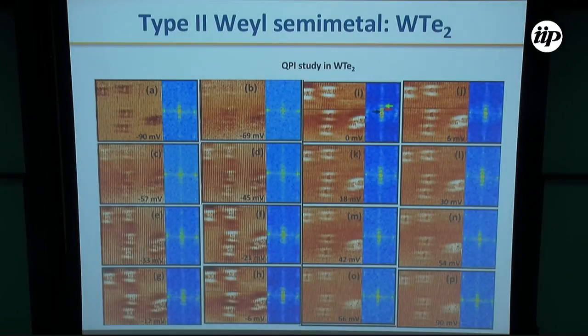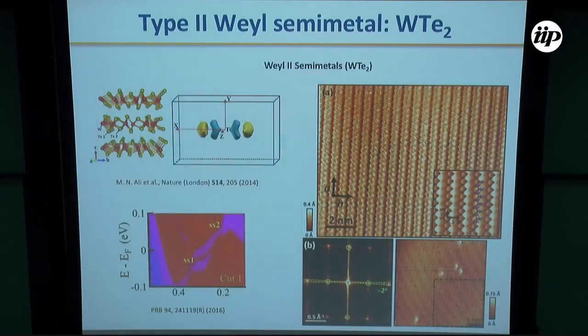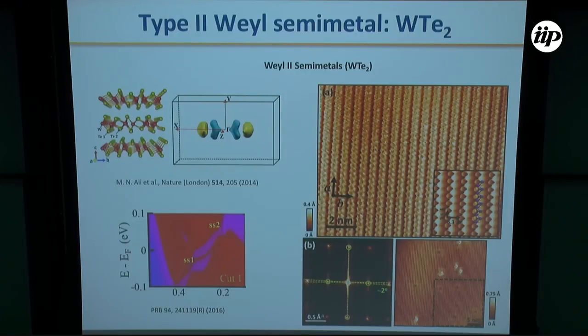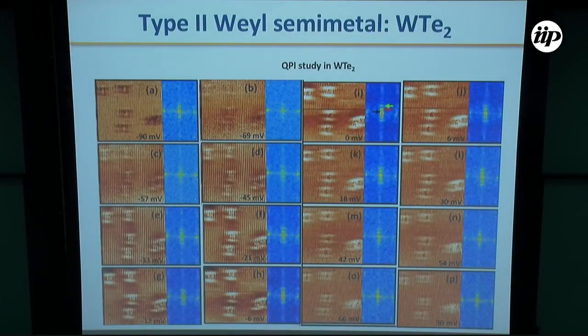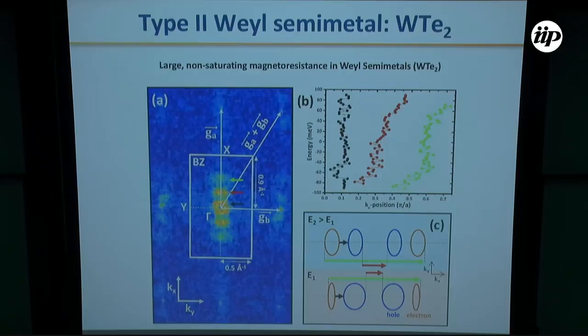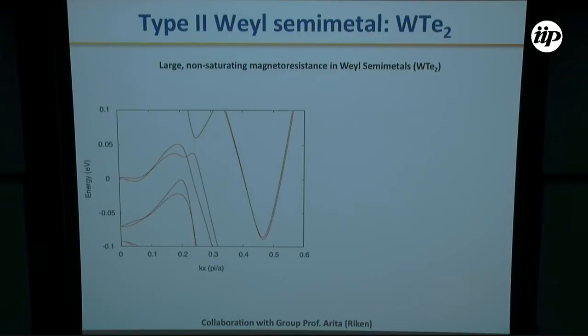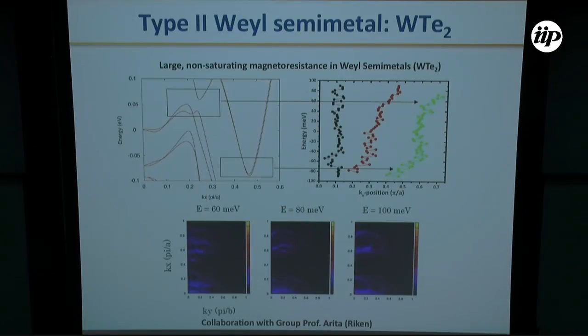When we look at the QPI signal produced by these holes in the lower part corner of the image, essentially what we find is three QPI vectors which are consistent and give information of the bulk band structure. We have started a collaboration with the group of Professor Arita in RIKEN. They have made band structure calculations, and they have also calculated the constant energy contours as a function of energy in the energy range that we have measured. Essentially, we can explain the energy dependence of the QPI vectors that we observe from the bulk band structure.